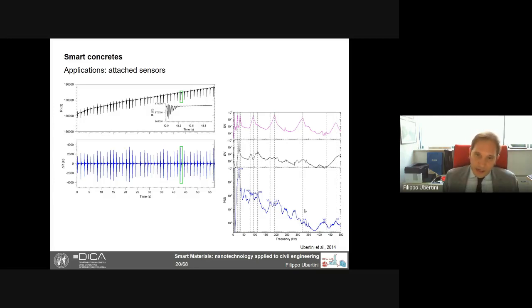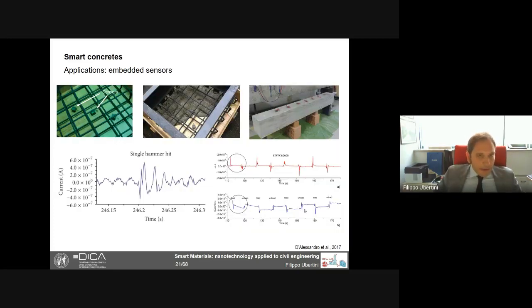So what we get here, and the first leading mode is quite evident, is that using these sensors, we can actually identify natural frequencies of structures. Of course, we have verified this also in embedded applications. So the sensors should be embedded into the molds before casting the concrete, and we have been doing this in different elements. For instance, on the beam that you see during curing time in the top right image, you see that there are some sensors embedded prior to casting, and on each sensor there is also a strain gauge to compare the measurement of the sensor with the measurement of the strain gauges.